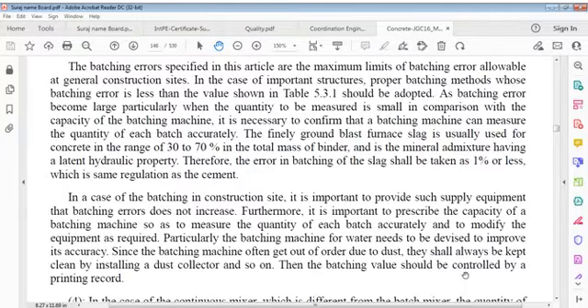As batching error becomes large, particularly when quantity to be measured is small in comparison with capacity of batching machine, it is necessary to confirm that a batching machine can measure quantity of each batch accurately. Finely ground blast furnace slag is usually used for concrete in range of 30 to 70% in total mass of binder, and is mineral admixture having a latent hydraulic property. Therefore, error in batching of slag shall be taken as 1% or less, which is same regulation as cement.